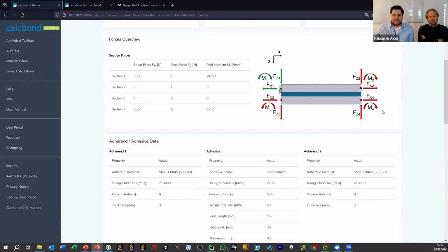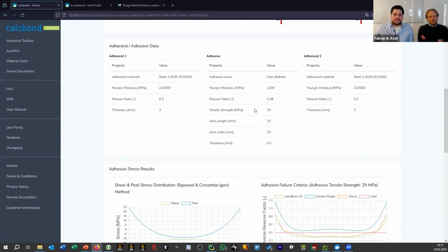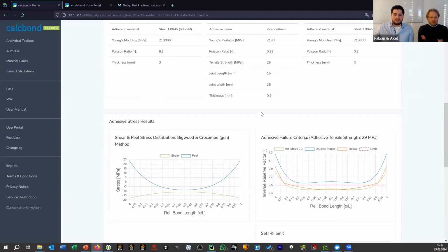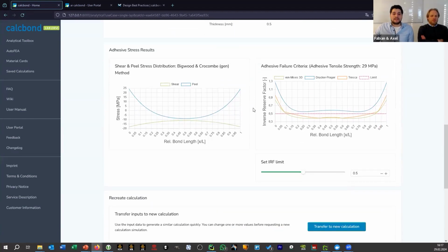Here I have an overview of the acting member forces and of the material properties of my joint definition. Scrolling further down, I have my adhesive stress results. What is important to note is that the analytical formulas go beyond the simple assumption of an average shear stress being distributed in this type of specimen, because they calculate a differential shear stress distribution along the bond line. We have these coordinates going from 0 to 1, representing the left edge of the bond line towards the right edge. And we see the green line here, a variation in the shear stress with peaks reaching their maximum at the free edges of the bond line.